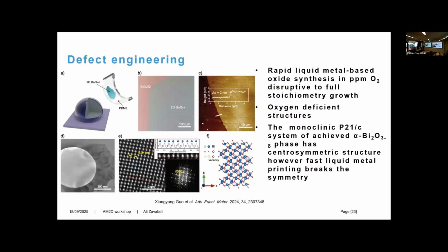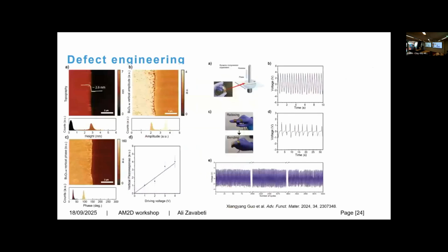what my students have shown in the lab is also for printing 2D bismuth oxides. If you reduce the oxygen content to ppm levels, about 10 to 80 ppm oxygen, and print in less than a second, you can break the centrosymmetry of the crystal structure. This specific phase of bismuth oxide is a centrosymmetric crystal that doesn't have the functionality. For example, it doesn't have piezo or memory performance, but we could print in low oxygen ppm as well as very fast printing to disrupt the full growth of the oxide layer. Therefore, we broke the symmetry and made a non-centrosymmetric oxide layer.